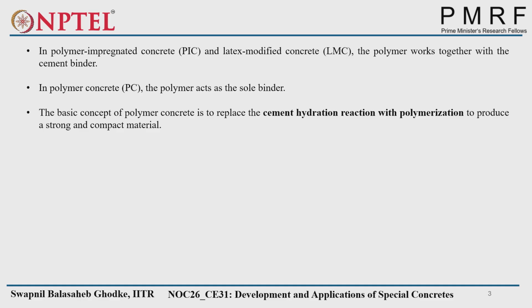So in polymer impregnated concrete and latex modified concrete, that is the third one, the polymer works together with the cement binder. But in the case of polymer concrete, the polymer acts as the sole binder because there is no water available. Although cement may or may not be available, water is not available. So cement will not hydrate if it is available, and that cement acts as a filler. It will only fill the pores between the concrete matrix. So the basic concept of polymer concrete is to replace the cement hydration reaction with polymerization to produce a strong and compact material. We know cement hydration is the process to get the CSH gel and get the hardened properties of the concrete. Similarly, to get the hardened properties of polymer concrete, we have to go through the process of polymerization. What is polymerization? We'll see in a couple of minutes.